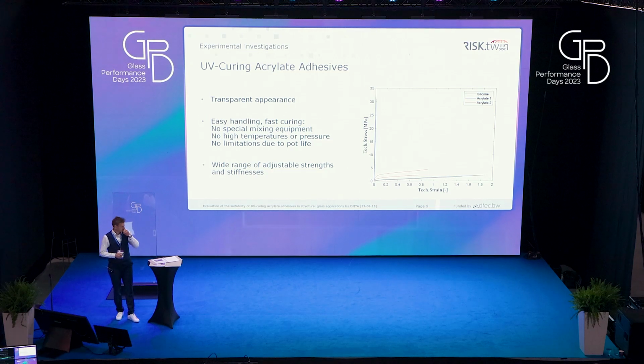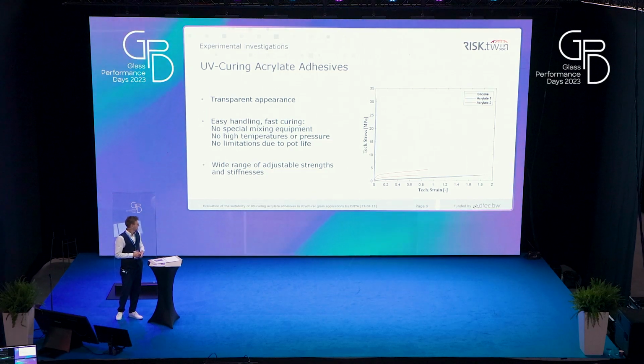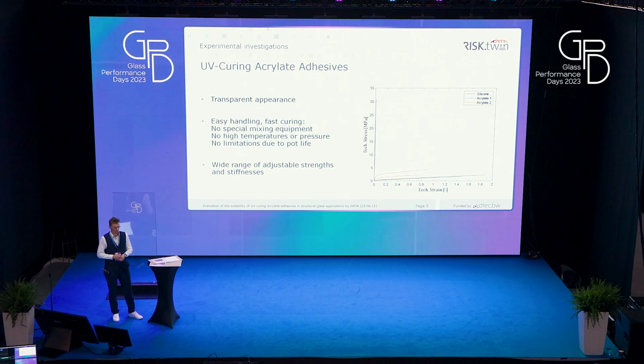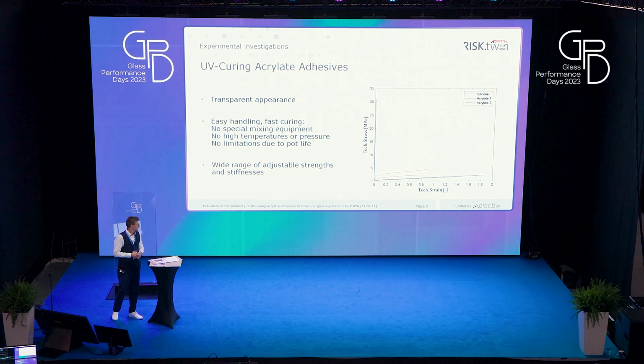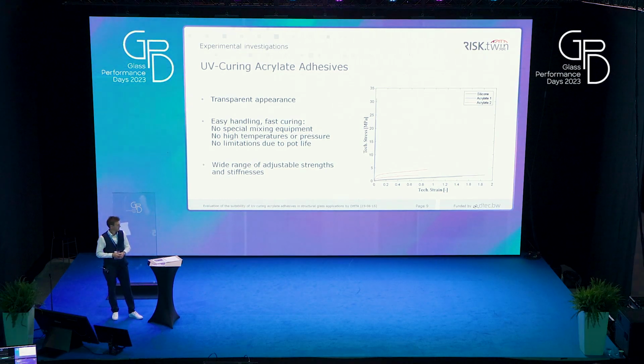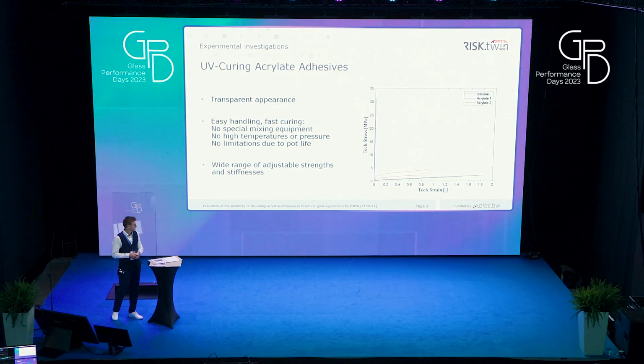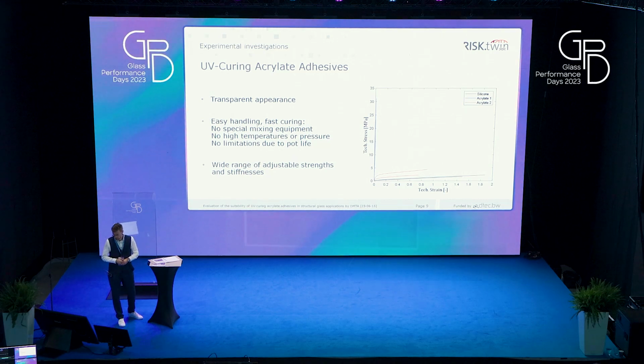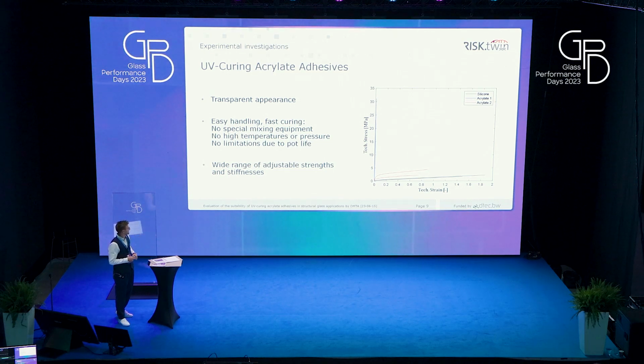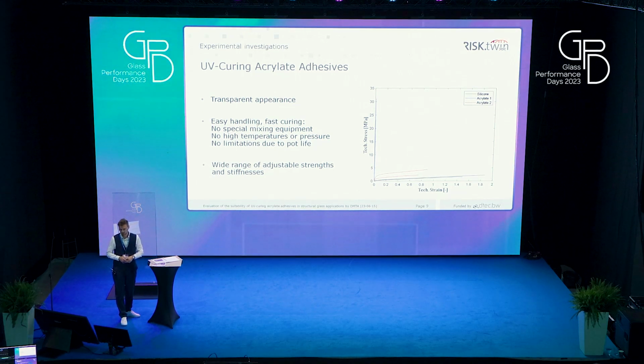This adhesive we just saw here is the red one in this picture. And as you can see, the maximum strains go nearly up to about 100%. The black line below represents a structural silicone, and here the elongation is even larger, but as you can see, at a significantly lower level in strength. And the third one, which I called acrylate 1, which I don't know if you can see, but it's the blue one right next to the y-axis. And so the difference between the blue one and the red one is the wide range of strengths and stiffnesses, which I was talking about.